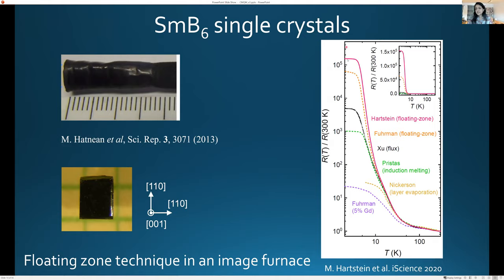Resistance ratios. And of our crystals, they bounce around somewhere between 10 to the 4 and above 10 to the 5. And so we only pick crystals to measure in high fields, which have a resistance ratio of above 10 to the 5, to make sure we're excluding as many dislocations or any impurities in the gap as possible.